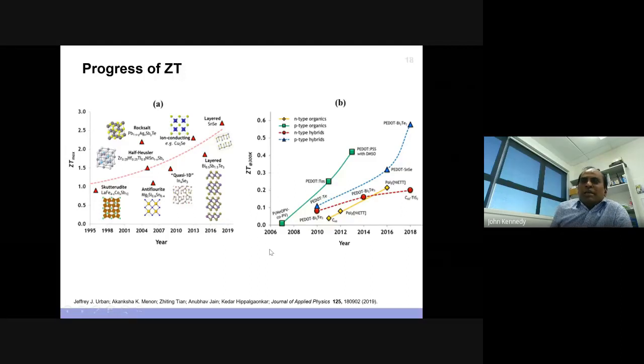But you can look at that diagram B, the efficiency is far lower than that diagram A. That tells you it's a long way to go ahead, because bismuth telluride is efficient. I mean, ZT is 1, which is the one first commercialized, and you can even buy it now, which is the one used in NASA satellite as well. But now, over the years, you can go to even other materials which can reach a figure of merit up to 2. So this is a typical challenging problem for physicists and material scientists to address.